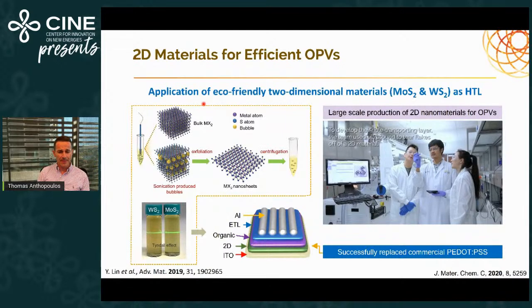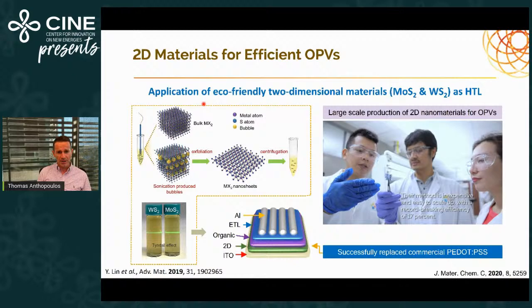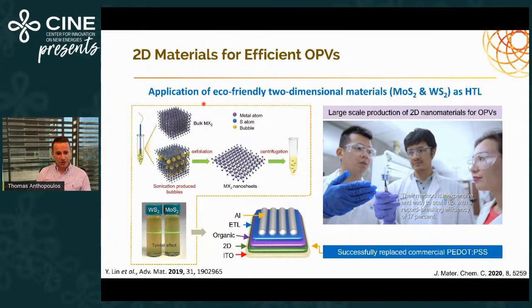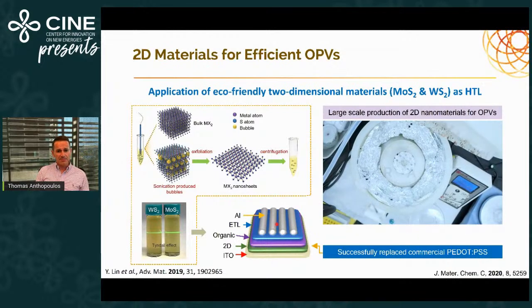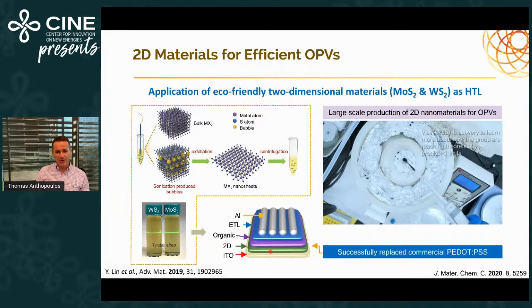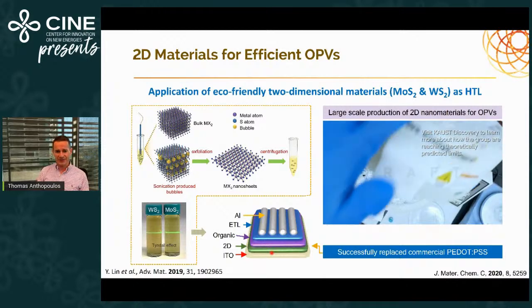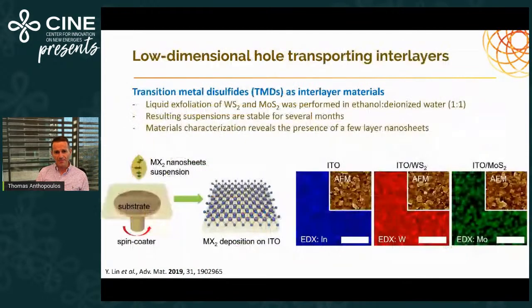You can take the powder, produce a suspension through sonication, and if you get everything right, you have a very nice and very fine suspension, which you can then deposit directly onto the transparent electrode, the indium tin oxide in this case. So this is exactly what we've done. And we realized we could form a very complete layer of these flakes of the 2D material over the ITO surface. It is very difficult to see any difference with the atomic force microscope. You see only a few nanometers change.